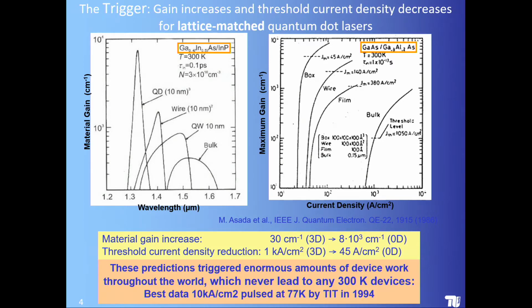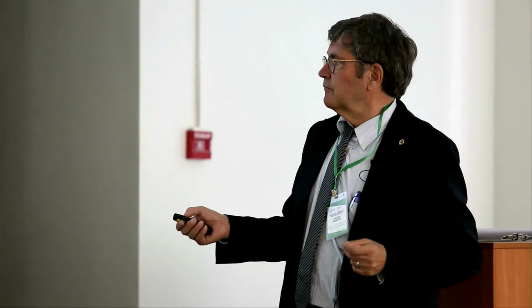Then he calculated for gallium arsenide embedded in gallium aluminum arsenide the threshold current density. And you see from 3-dimensional down to 0-dimensional, the threshold current density decreases. Yeah? And that's, of course, a very important number for any light-emitting device. The transition from spontaneous emission to stimulated emission is the most important number, because up to the break point here, where stimulated emission starts, most of the electric current which is injected is just creating heat. And only here, and this is a double logarithmic scale, only here you are at a moment when any additional electron-hole pair which is injected can leave the device as light.